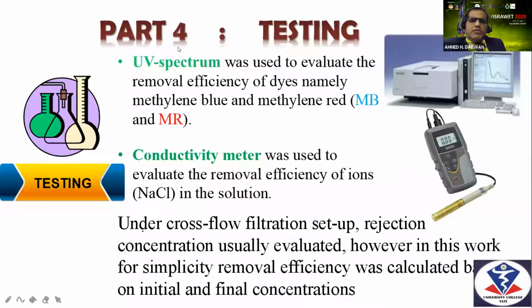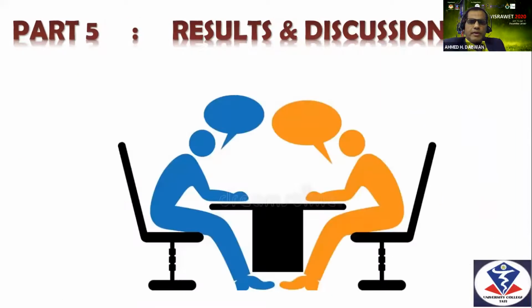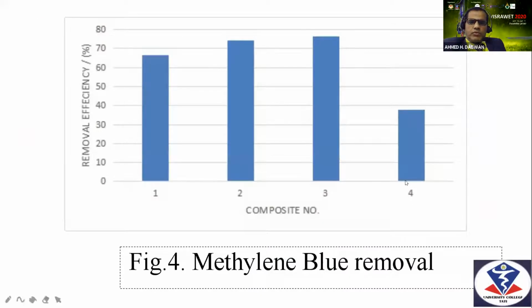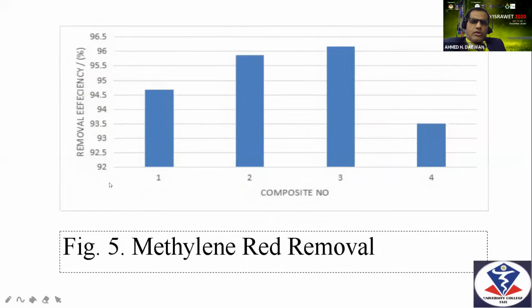After analysis, we take two measurements. One is testing by UV. We use dyes, methylene blue and methylene red. And we also check the conductivity. We take seawater, make a dilution, and check how much salinity is removed. Here you see methylene blue removal was almost 80% for sample number 3, or 75. And for methylene red removal, we got about 96 or 97, almost complete removal with sample 3.